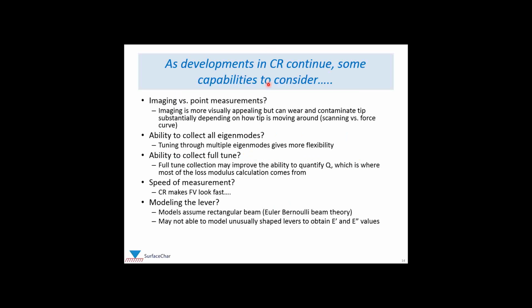So that work was from approximately 5 years ago. And there have been a lot of developments in contact resonance, and these are some of the capabilities to consider in contact resonance today. First, are you doing imaging or point measurements? Although imaging is more visually appealing and can generate pretty pictures, imaging can wear and contaminate your tip substantially, depending on how your tip is moving around. So sometimes point measurements are a much better way to go.